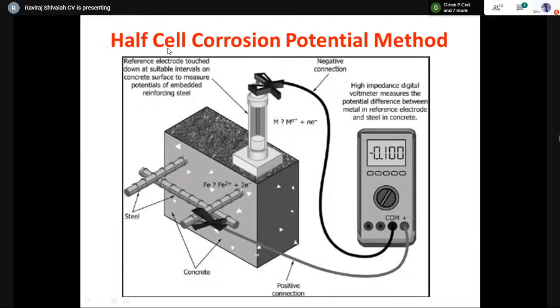So we have two half cells here. The first half cell is the electrode over here, where a copper rod is dipped in a copper sulfate solution, and this is kept on the concrete surface. Now, this electrode is attached to this voltmeter, that is the instrument, and from the instrument, again, a lead goes and gets connected to a reinforcement anywhere in the concrete surface. So that means this particular test primarily necessitates you to open the reinforcement at some particular location, and then anywhere in the slab, or in that particular structure, the instrument should be attached.